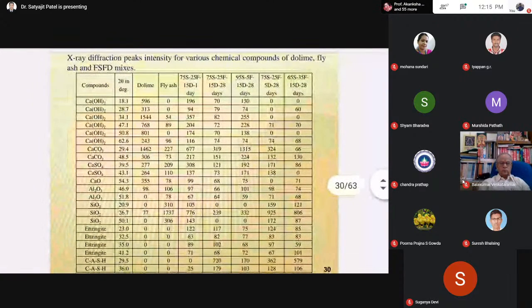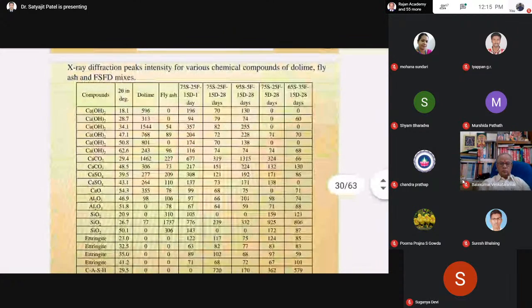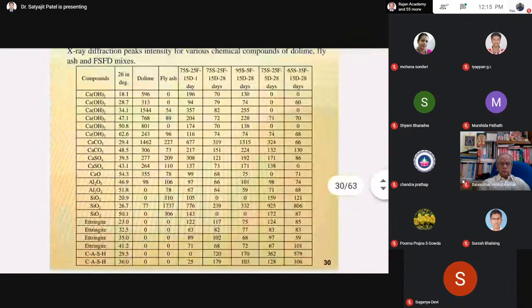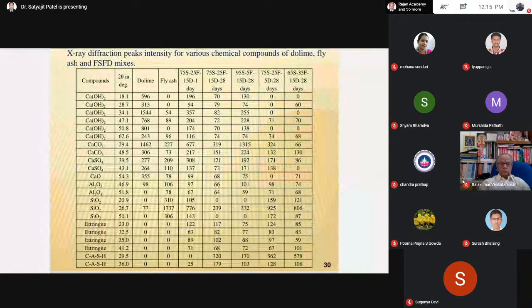For this different material, steel slag fly ash dolomite at 1 day, this is the X-ray diffraction peak intensity. From the XRD test, I have compared the XRD peak intensity of different mixes and different curing periods. The different minerals or compounds are calcium hydroxide, calcium carbonate, alumina, silica, ettringite, and CASH gel, calcium alumina silicate hydrate. This binding gel is responsible for the strength gain or the increase in stiffness of the material.